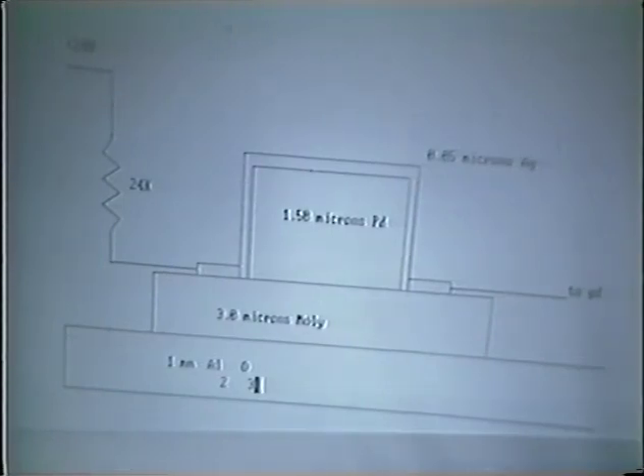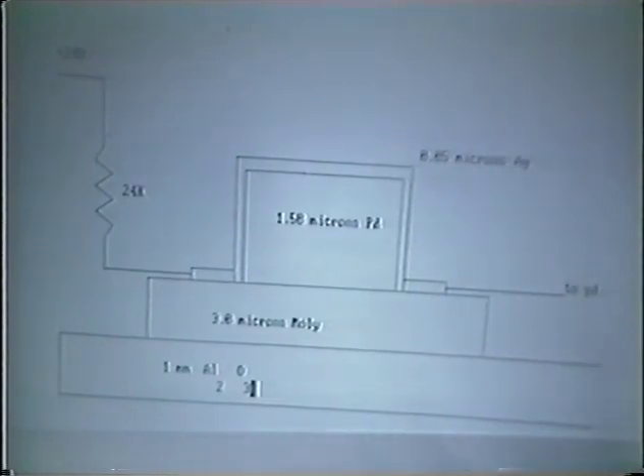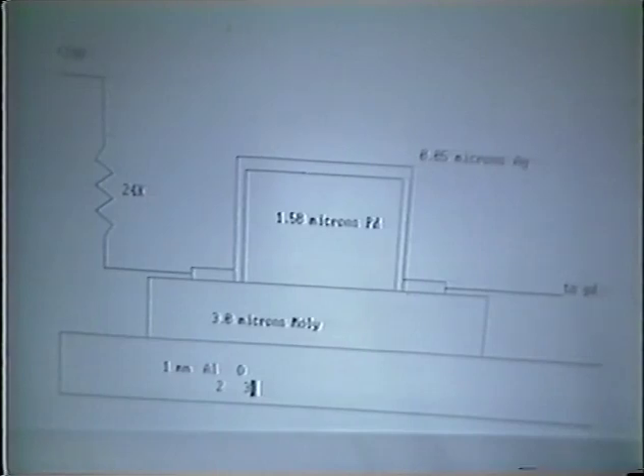The reason for the insulating substrate of alumina was we wanted to run current through it, and we wanted to make sure the current went through the actual targets. So between the 3 microns moly and 1.5 microns palladium, about 2/3 of the current that was run through here, 1/3 went through the palladium. In addition, a very thin layer, 0.05 microns of silver, was splashed on top. This is to optimize the loading on the assumption that some of the implanted deuterium without a surface coating might actually diffuse through the surface.